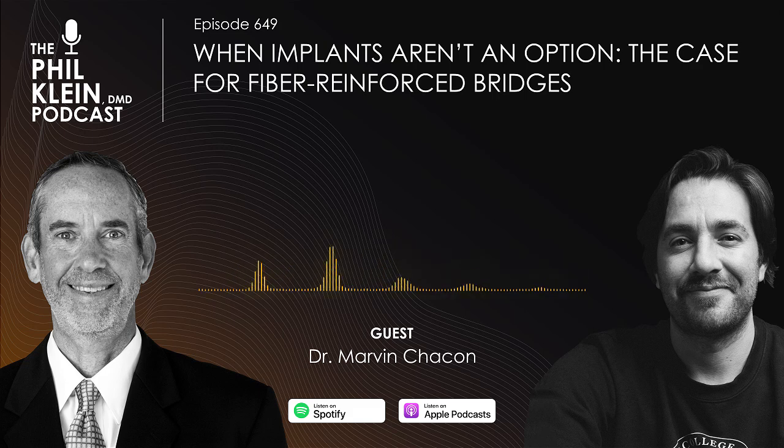Sure, doctor. Well, fiber reinforced bridges are fixed prostheses composed of two parts. The first one is the framework made from the fiber chosen by the dentist, and the second part is the veneering material, which is used to fabricate the pontic. The choice of veneering material depends on how long the dentist wants the bridge to remain in the patient's mouth. If they're looking, for example, for a long-term provisional solution, let's say 1.5 years, they can use a last generation bisacryl. If they want a definitive restoration, they should use resin composite. Okay, bisacryl. Exactly. Yes.